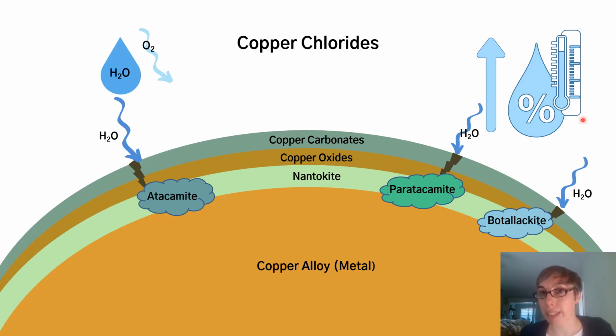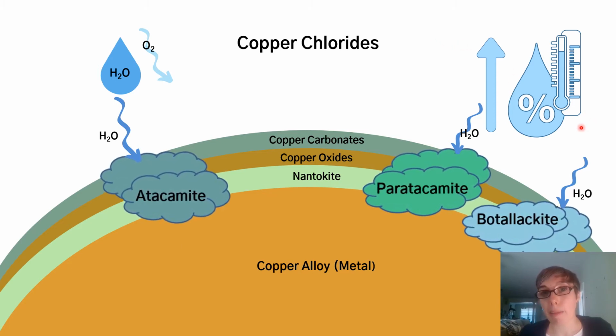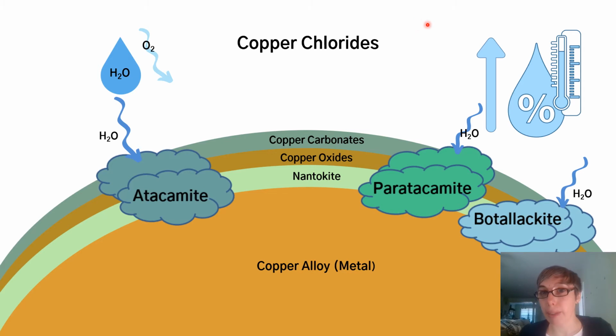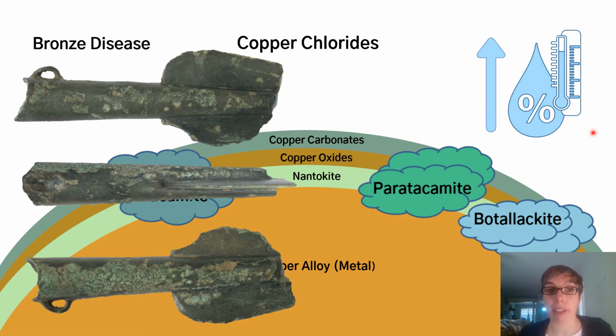These copper chlorides take up a lot more space, physically speaking, than the nantokite, which causes them to literally erupt from the surface of the overlying patina layer, often destroying the surface of the artifact that is preserved in those layers. This phenomenon is often called bronze disease, as you can see demonstrated by these artifacts, and it is extremely pernicious, and once started can be very difficult to stop. In the worst case scenarios, it often results in catastrophic damage or complete loss of the artifact.